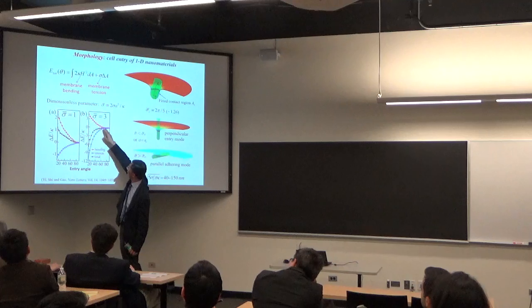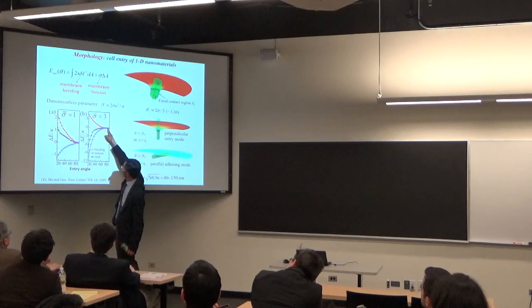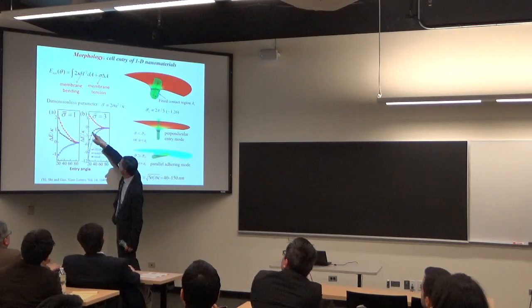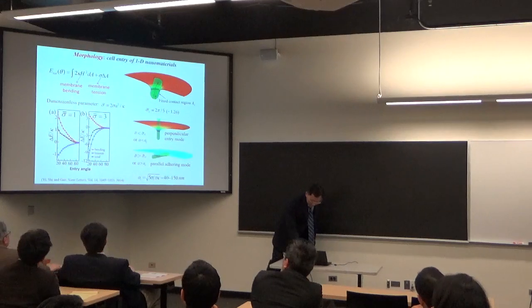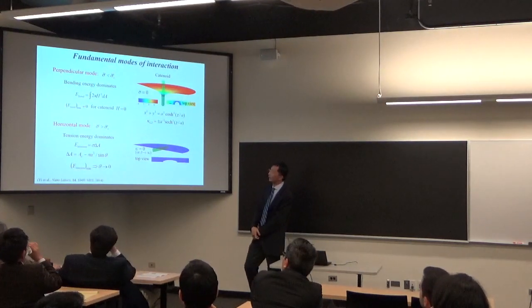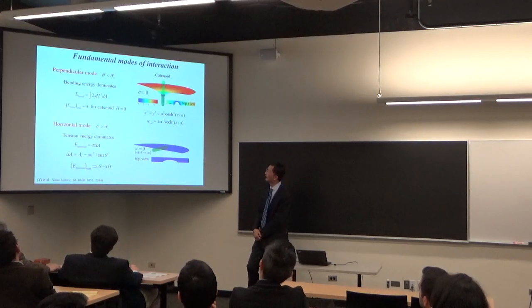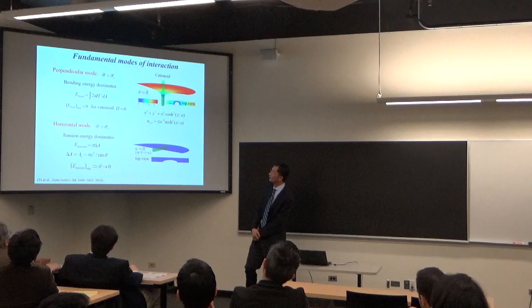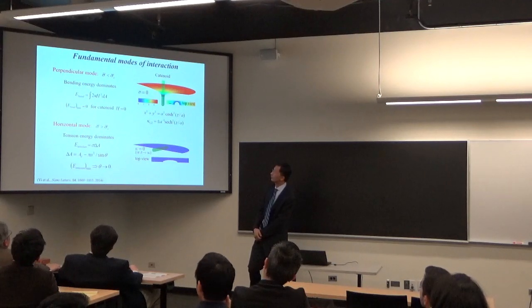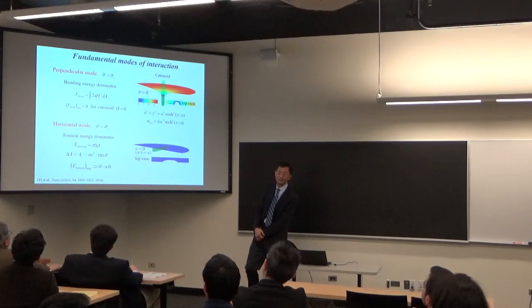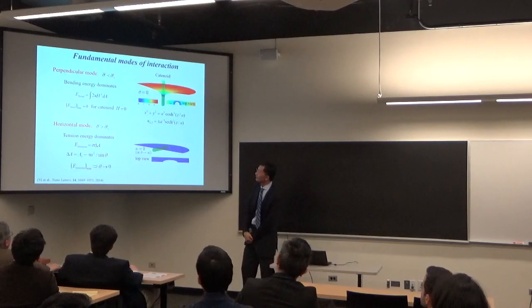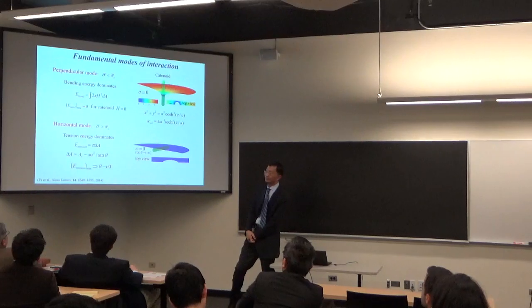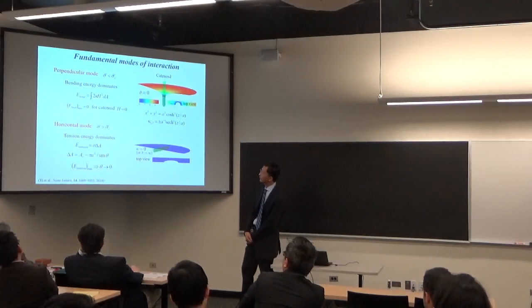In the supercritical case, when sigma equals 3, bigger than 2 pi over 5, the bending energy still favors 90 degrees, but the tension energy becomes dominant. So the total free energy is minimized at a very small angle. This can be understood by some simple analytical formula. Consider the extreme subcritical case, when the non-dimensional parameter equals 0, meaning there's no membrane tension. Bending energy dominates, and we only have bending energy. Since the energy is positive, the minimum energy surface corresponds to a mathematical surface called a catenoid.